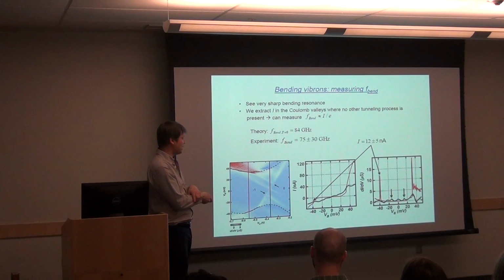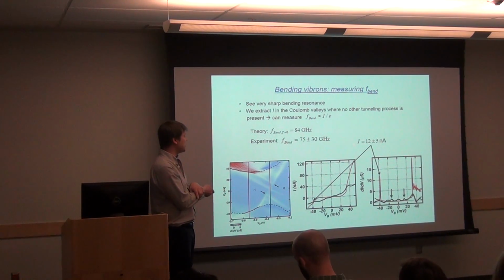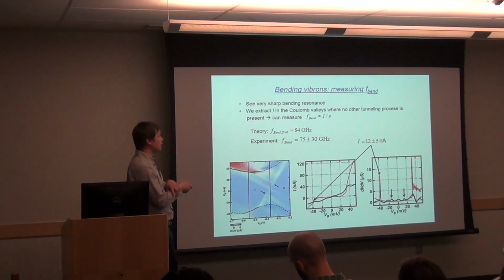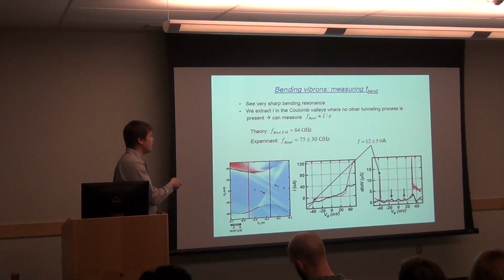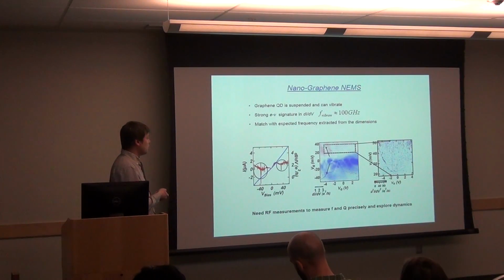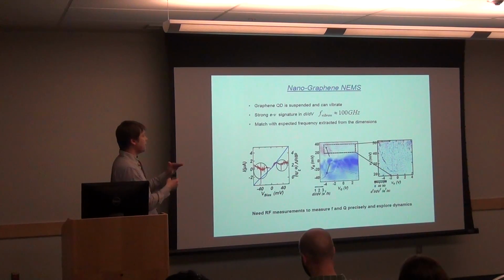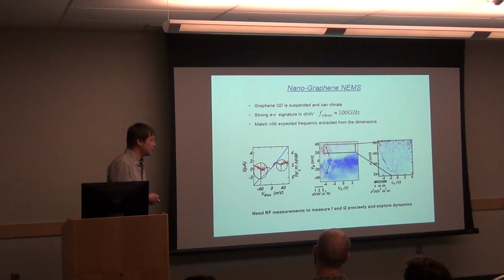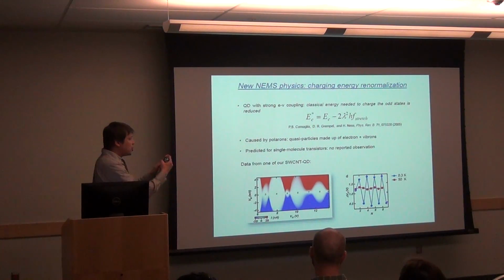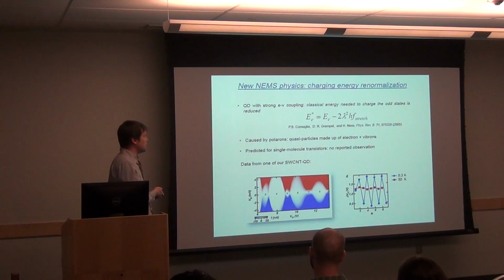If you look at the dI/dV, you see very sharp resonances in the transport, and the frequency of the current matches the bending mode from the length of the system. In this case, they're 80 gigahertz, and we could do even higher frequencies. We saw something similar, although this is unpublished, in graphene, because there we don't have sufficient data to see it, but basically in small pieces of graphene, we think we also see these mechanical modes at about 100 gigahertz, but the data is not as conclusive so far. So we could use strain, for example, to tune these systems.